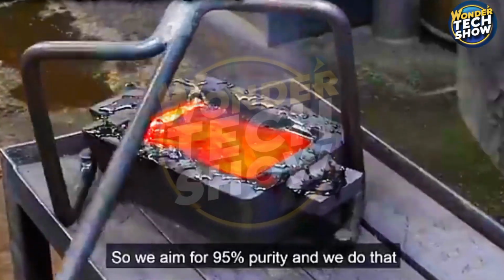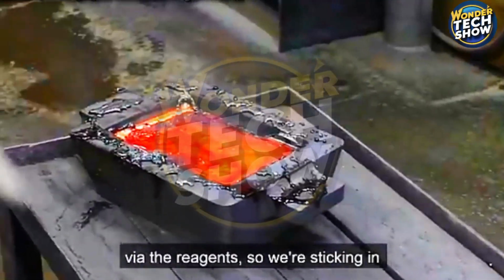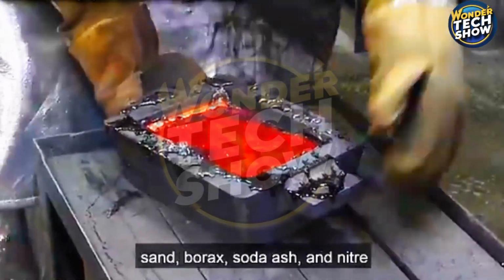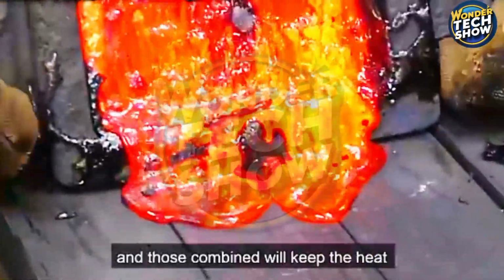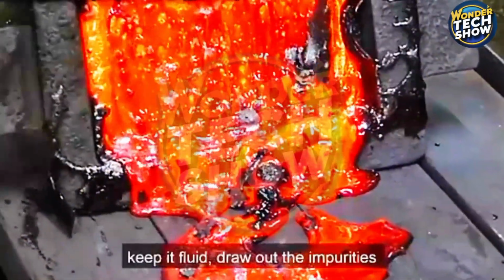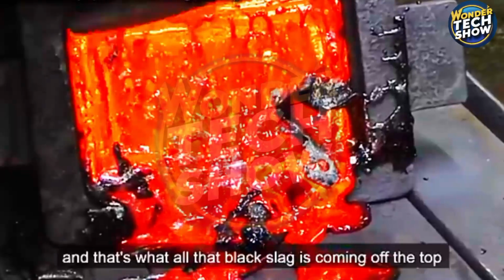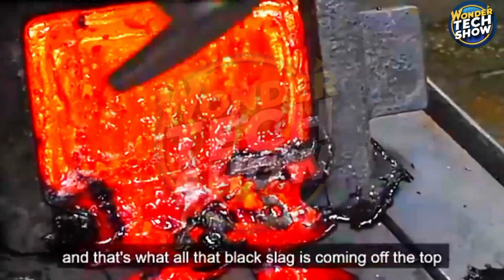So we aim for 95% purity, and we do that via the reagents. So we are sticking in sand, borax, soda ash, and niter, and those combined will keep the heat, keep it fluid, draw out the impurities, and that is why all the black slag is coming off the top. So it is not gold, it is black like obsidian.